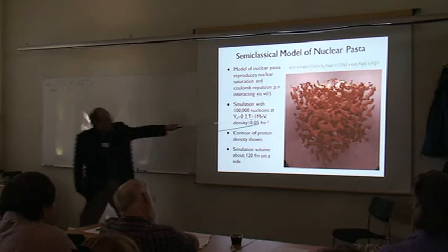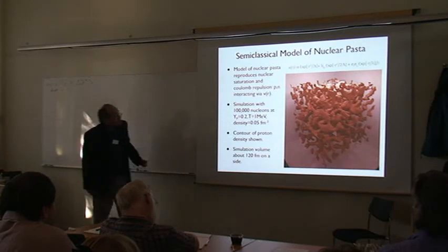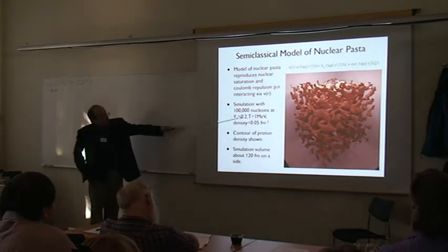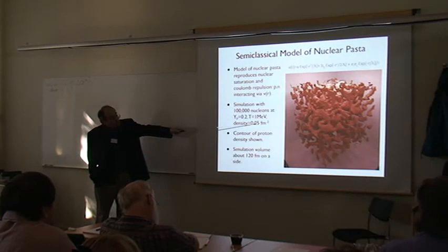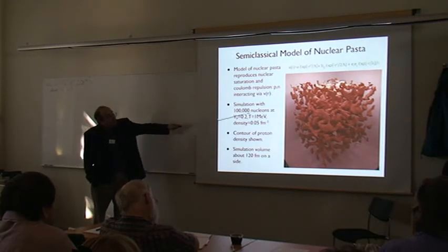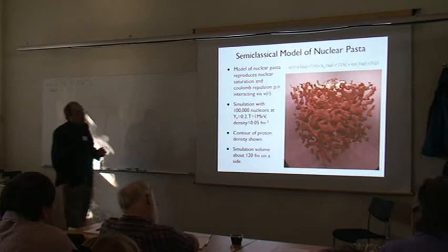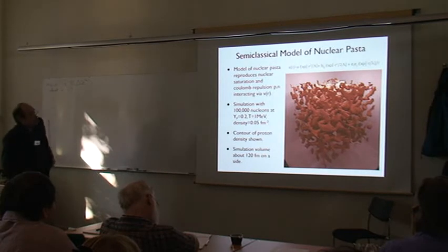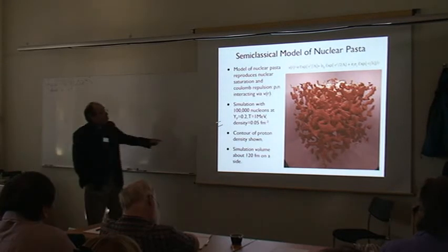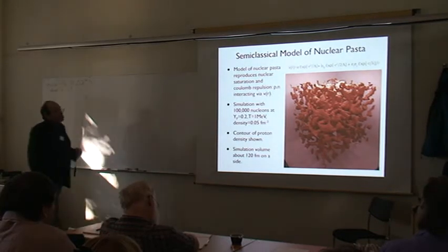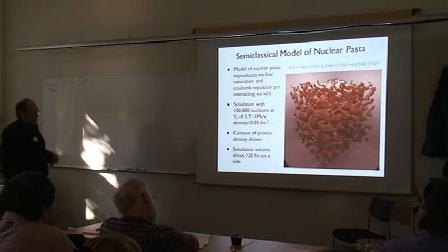Here's an example of the proton density in our simulation. This is about a third of nuclear density. This particular case had a proton fraction of 0.2, which is a little high for an isolated neutron star, maybe a little bit low for a proto-neutron star during a supernova.